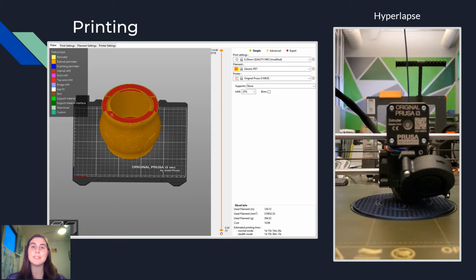Now that last one you see is the infill, 25%. This is the most optimal infill we found after conducting various tests with samples in which we determined that it would not provide any sagging with the holes or provide any poor surface quality, while still giving it that good structure and being lightweight. Now, the nice thing about this program is at the bottom, it does show you how much filament is used. So we used 394.53 grams of filament for this one print. And that took us approximately 1 day, 15 hours, 10 minutes, and 26 seconds to print.